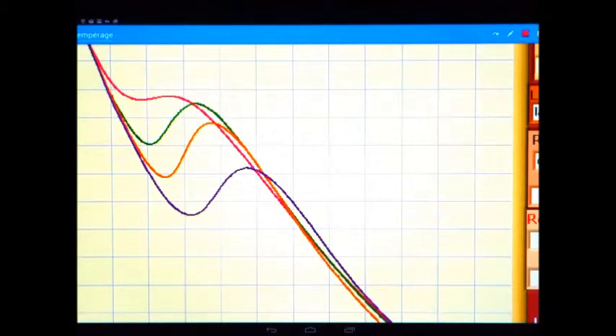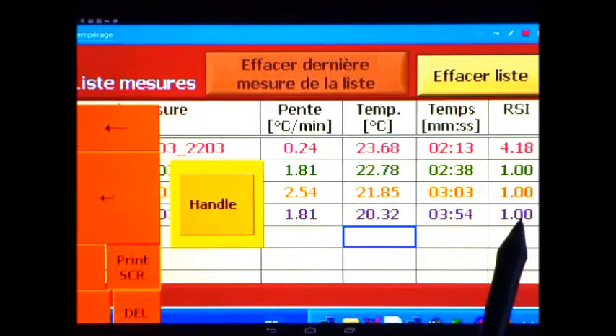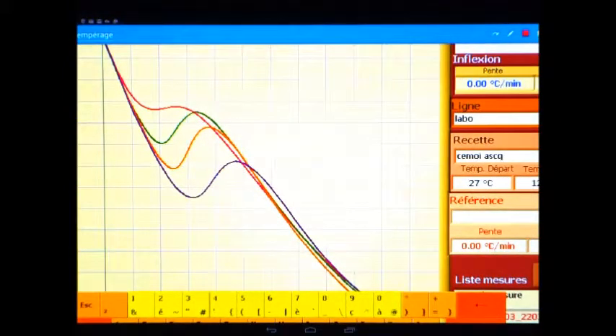Note also that we may have similar or identical slopes, like the green one and the violet, and a start of the exothermic at different temperature levels. The index is no longer telling us anything about the amount of crystals. If we have a look at the index, we have an index of 1. Integrating the information on the starting temperature of the exothermic, we can conclude that for the purple curve there are even fewer crystals than for the green, as the start of the curve is much lower.